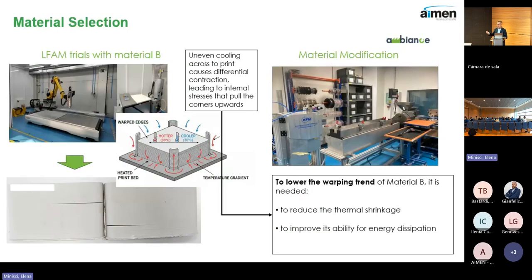So, once we selected material B for going to the large scale, the next thing was to do actual fabrication trials in the large format fabrication cell that we have here at AIMEN. And as we could foresee from the rheological analysis, we observed warping and delamination. So what are the causes of warping? There are two main reasons. One is more physical and the other is more physical-chemical. The first reason is thermal contraction, since all materials contract whenever they cool. And this is something that we had somehow controlled by adding fillers.